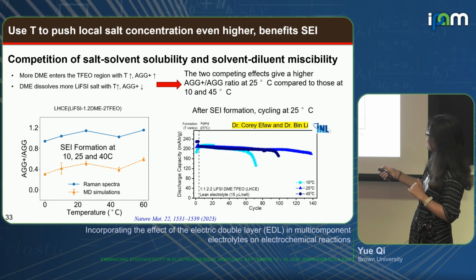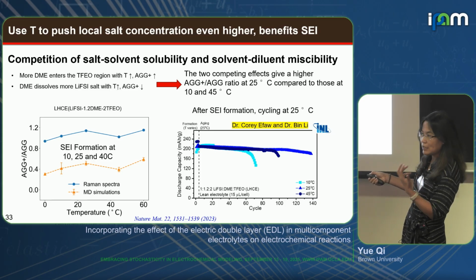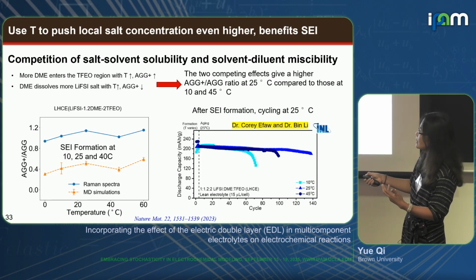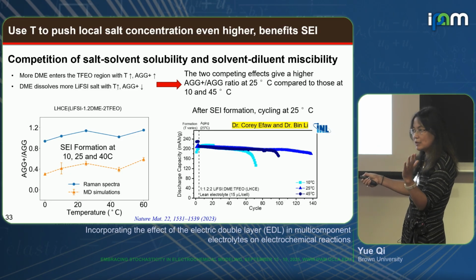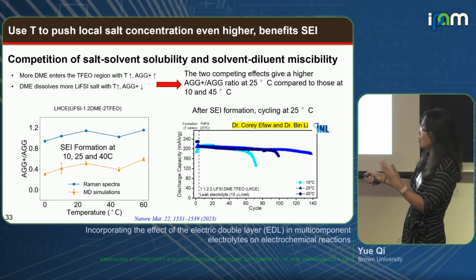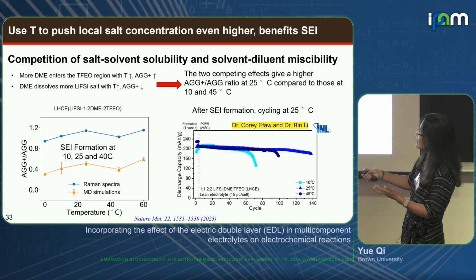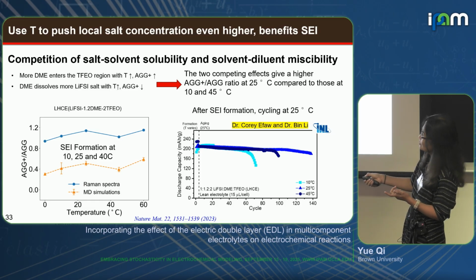And then after you form this SEI at different temperatures, the one formed at this temperature cycled much longer than other formation conditions. It's interesting, after we calculate this, we say if we keep increasing temperatures, you have more solvent mixing with the diluent, and finally you'll start to increase the aggregates again, the salt concentration in those clusters again, and then they also saw that. But we are not going to form at this temperature yet, because there are too many side reactions.